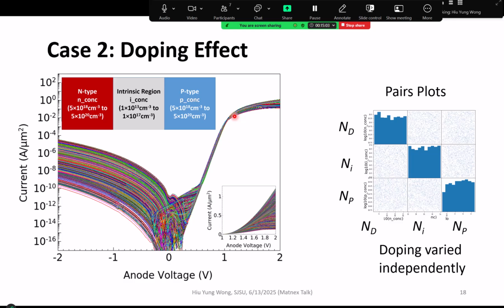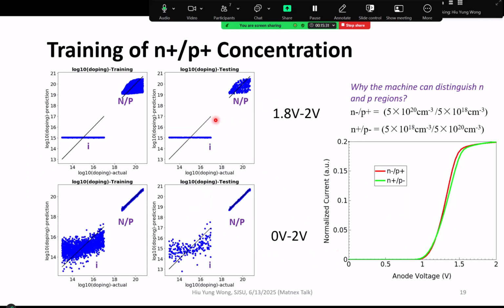So another trial is, what if we only change the doping concentration of this region? Now we see that besides a big variation in the reverse part, we also start seeing variation in the forward part. If you put it in linear scale, you see that for different doping levels, we get different forward currents. So just now I said that we cannot predict that well if we just use those curves, but now with this doping, let's see what happened. Indeed, we were able to predict them well.